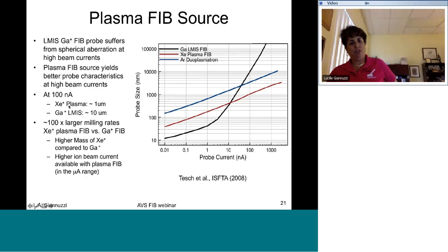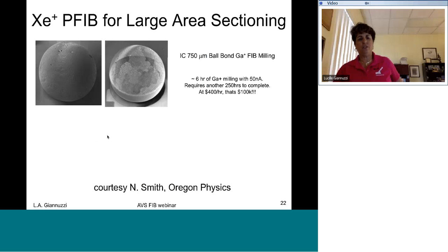Okay, so just to compare the two, at 100 nanoamps, the xenon plasma FIB gives about a 1 micron beam. Gallium with a metal source gives about 10 microns. So what this means is that you've got 100 times larger milling rates on the xenon plasma FIB versus the gallium FIB. And you get sort of a 2-for-1 punch here. One is that you can go to higher milling rates with the xenon plasma FIB, and two, because the xenon is heavier than gallium, you also get an additional factor of higher sputtering. So two effects there: the larger beam current that's available, as well as the larger mass by going to xenon.